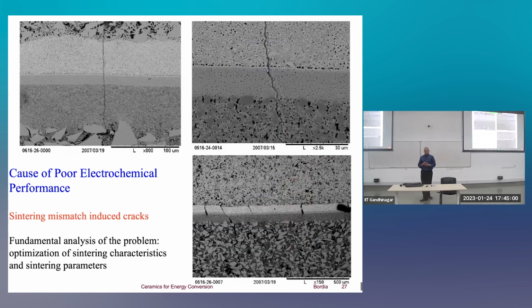We worked with them for many years, looking at their production processes, trying to identify the reasons for this low performance, because the material system that they were using was a good material system. And we found that because of the way they made these, they had defects in their fuel cell. These are due to what we understand well as constrained sintering, where you are trying to densify these different materials together, and that results in cracking of these kinds, because the processing had not been optimized. And these cracks actually serve as essentially short circuits. So the fuel just goes through the cracks rather than doing its electrochemical work. And as a result, the power performance is rather low, right?